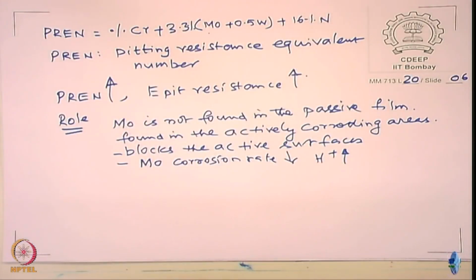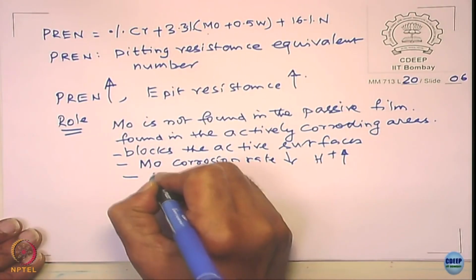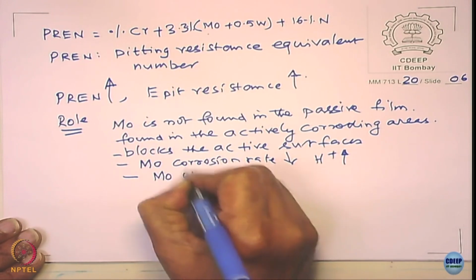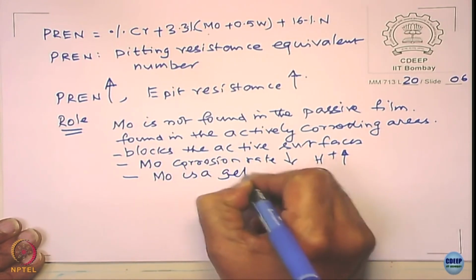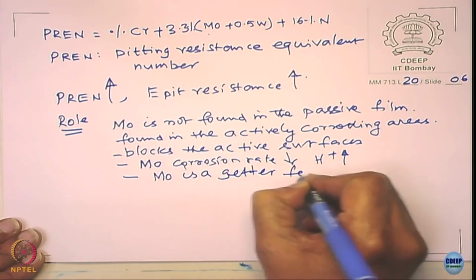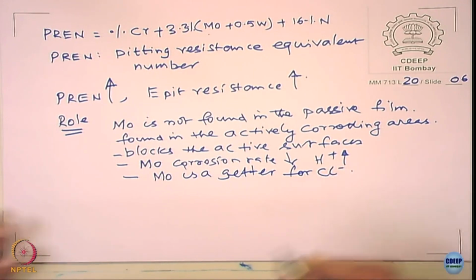This is considered as another kind of factor. Other people call molybdenum a getter for chlorides. It can complex with the chlorides. Chlorides are the species which promote corrosion, right? In the pit you have more chlorides, and the molybdenum forms a complex with the chlorides, and so what happens? The free chlorides are very less, and so pitting is decreased.